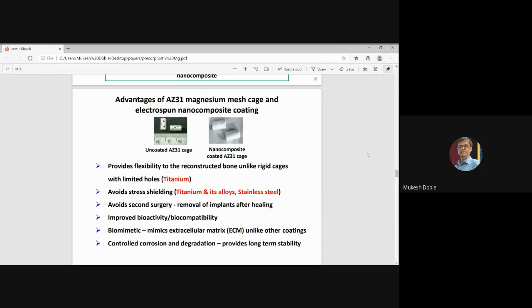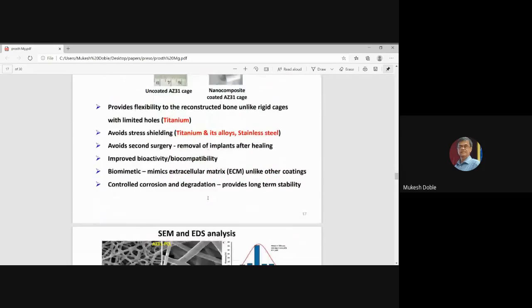By having different amounts of this PCL HA coating, we can control the degradation of the magnesium. We can either slow down the degradation or we can speed it up by designing the thickness of the layer of the coating of PCL. Okay, so if you want a 6 months disappearance, or if you are looking at 1 year, 1.5 years, and so on, actually, that's the advantage.